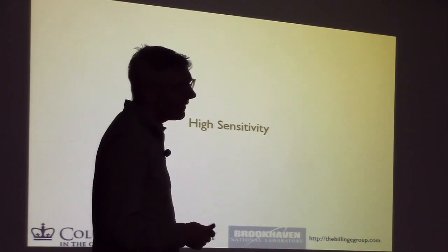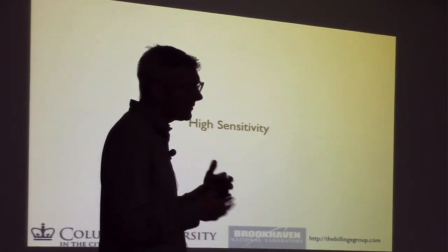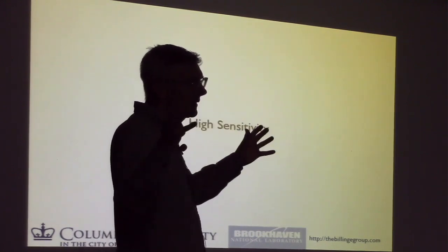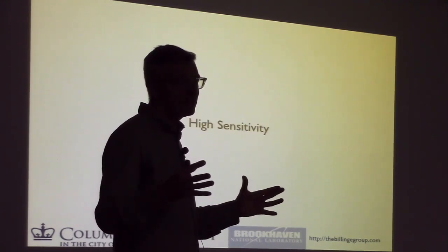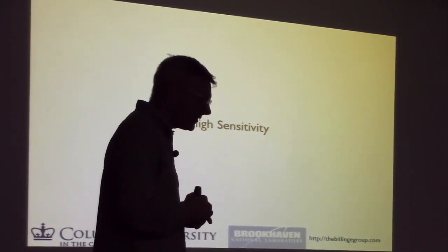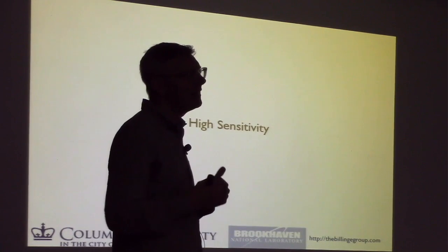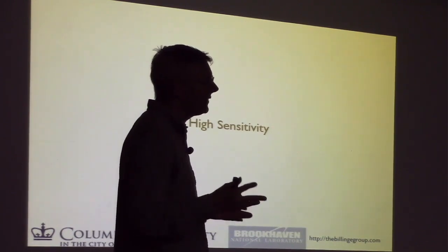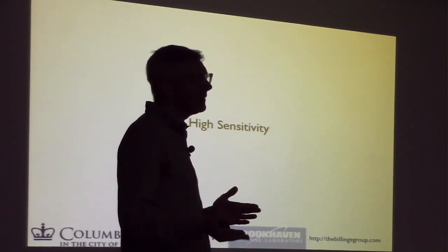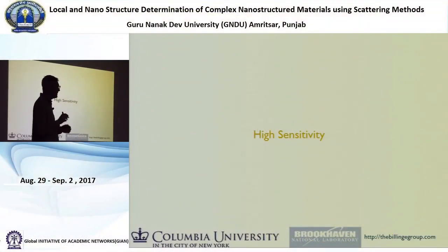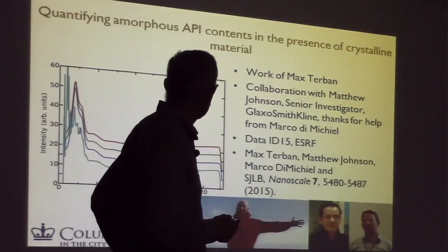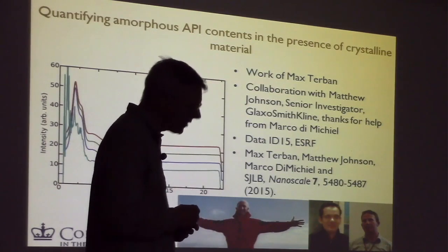Now, something else that we've been pushing very hard on is the sensitivity of the measurement. So sometimes you have a nanoparticle that's embedded in something else, maybe a nanoparticle inside glass or something like that. And people would ask us, what's the smallest amount of material that you can measure? And we used to always say, well, if there's 5% of material, we can see it. If there's 1% of the material, we're not so sure. But we've been working very hard to increase the sensitivity. And so by collecting data with very high statistics and then using some advanced computational data processing methods, we're actually doing much better. And so this was a project which demonstrates this.